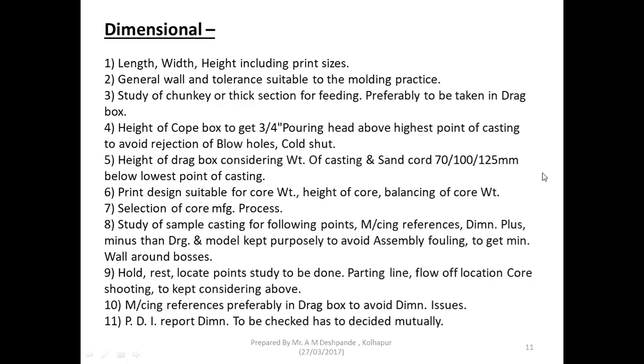Print design suitable for core weight, height of core, balancing of core weight, selection of core manufacturing process, study of sample casting for the following points: machining reference, dimension plus minus, then drawing or model, which are kept purposely to avoid assembly fouling and to get minimum wall around bosses. This is most important. Point number 8 is most important, at least for all automobile castings, because as per model, if we do, we may face problems of fouling in assembly.